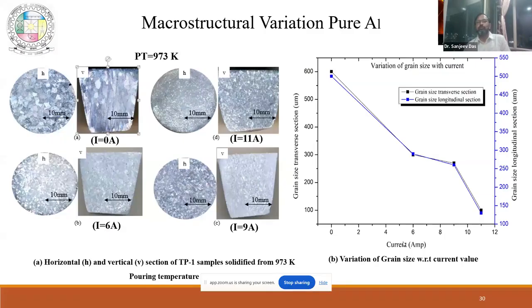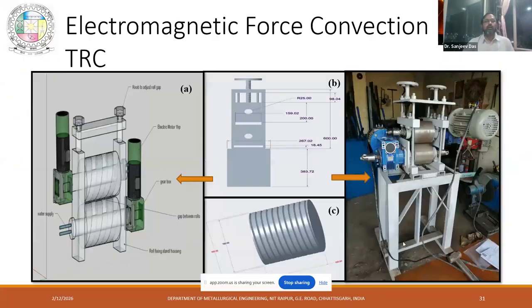Now this is the beauty of it. It is not about how much grain refiner you have to add. It is about how much current you are giving to the liquid metal during solidification, and it will create the magnetic field, the stirring effect, and finally decrease the grain size. So we are completely eliminating the presence of grain refiner here. Now that is the test procedure.